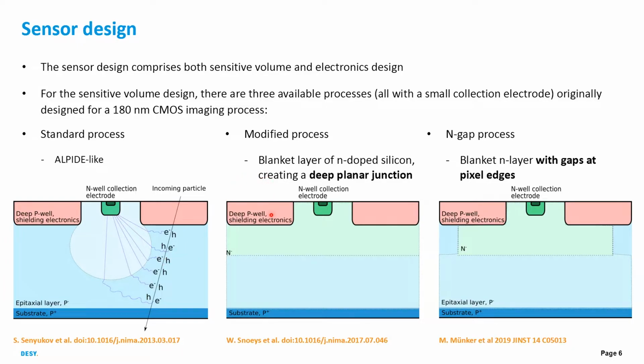So that's where the modified process comes in. It introduces a blanket layer of n-doped silicon, which creates a deep planar junction here, and depletion then grows from this junction. And this way we deplete under the p-wells as well. However, the field lines at the center of the p-well, so edges of the pixels, become very straight here, and we'd rather they push the charges a bit more towards the collection electrode, and this is where the n-gap process comes in. So it leaves a gap in the n layer, and this introduces a vertical junction which makes the electric field lines push the charges more towards the collection electrode.